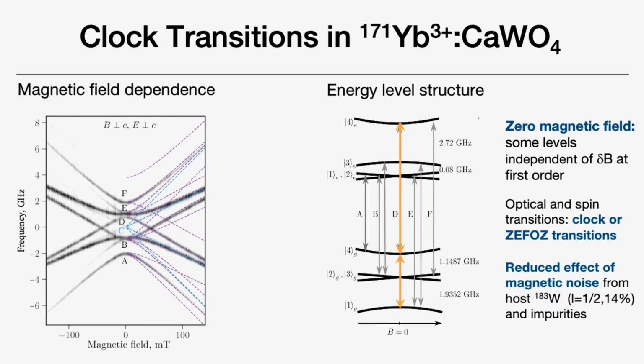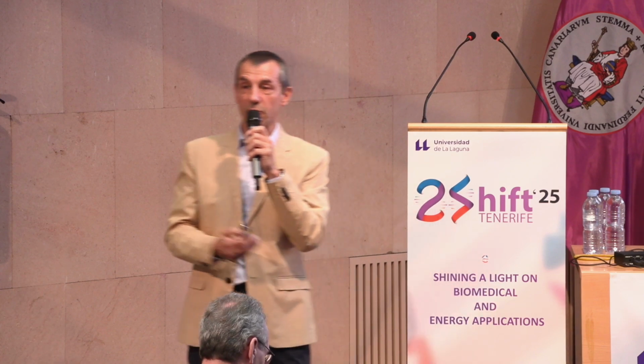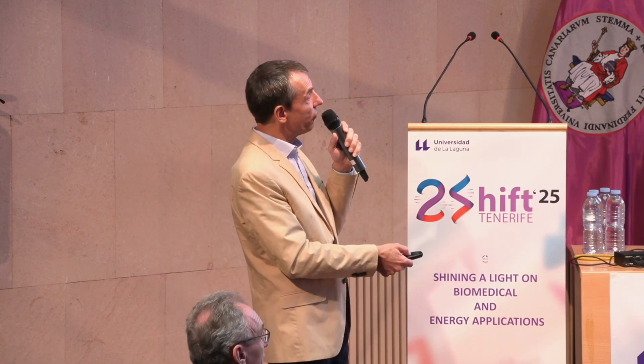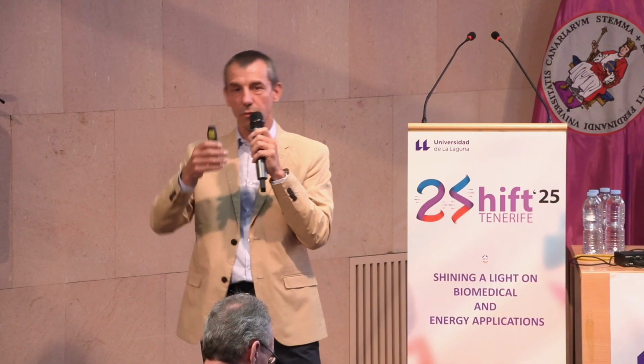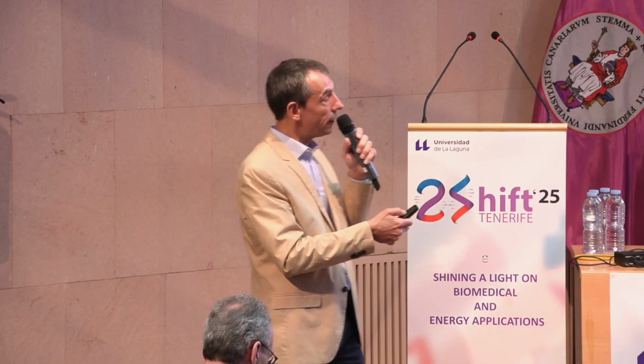And why is it interesting to have transitions which are insensitive to magnetic field fluctuation? It's because you will have a very much reduced effect of magnetic noise in this case, because we have these flat curves here. And why are we concerned with magnetic noise? Because in the host, we have nuclear spins. They come from tungsten-183, which also has 1/2 nuclear spin, with 14% abundance in the natural compound. These spins will fluctuate even at low temperature, go up, go down, and this is causing magnetic noise, which couples to the transition of the rare earth ion and causes perturbation to the quantum states, and ultimately can limit the lifetime of these quantum states.